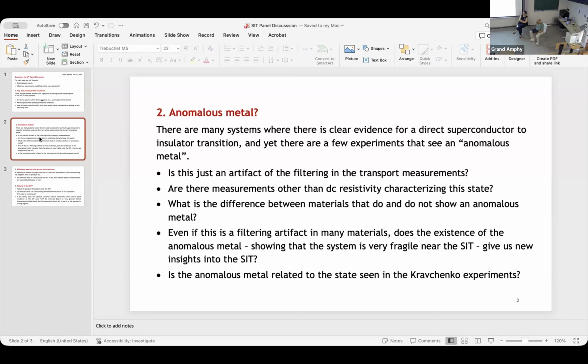One of the things that we had observed both for niobium nitride and molybdenum germanium is that when you start putting in disorder, the initial suppression of Tc appears to be fermionic, in the sense Tc scales with delta. But in both cases, when you go to strong disorder, at some point Tc keeps decreasing, but delta roughly remains constant. But then if it goes to a metal, delta must collapse discontinuously. So it is bosonic.